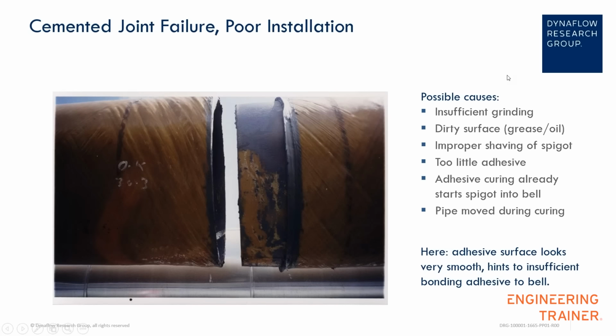Here we see an example of a bell and spigot joint that failed. But what is interesting here is that the surface, here you see yellow is the pipe surface, the surface of the spigot, and then black is the surface of the adhesive. And the surface of the adhesive looks very smooth, so it looks like there was little bonding between the bell and the adhesive. If there was good bonding, then you should still see some traces of glass that bonded, and there should be more rupture of the fibers, maybe due to poor grinding or maybe due to curing that starts too early. But at least you can conclude from this photo that the joint was not of good quality due to